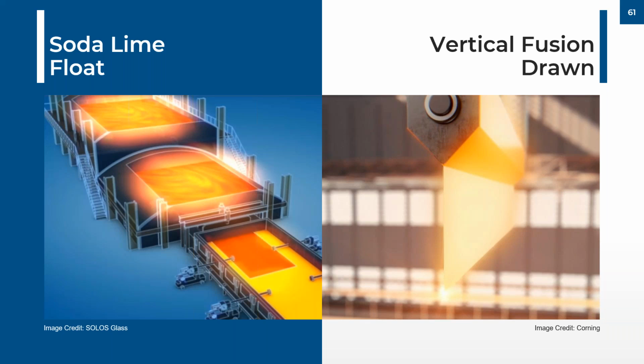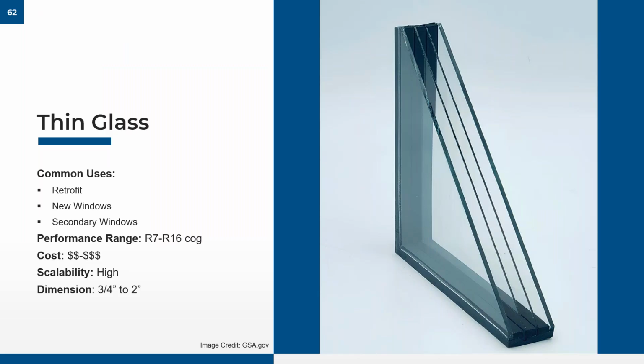very much like a regular glass. It can be made a couple different ways, such as regular float glass, which is commonly referred to as soda lime float glass. There's a different manufacturing process for thin glass, which is a vertical fusion draw, where molten glass is poured into this isopipe and then it spills out both sides. And as they drop down vertically, those two sheets fuse together, and as it drops vertically, it cools at the same time. It's cut, it's put off to the side, and then manufactured into whatever it needs to be. This is really how it gets to be so thin, very, very thin.